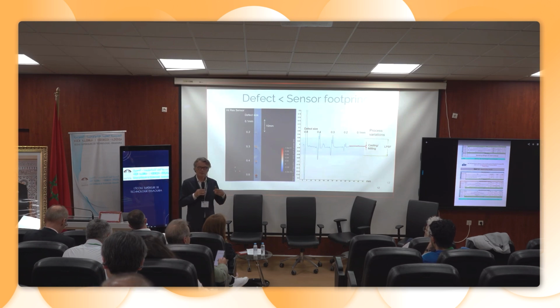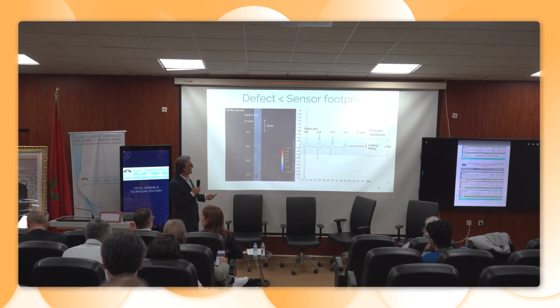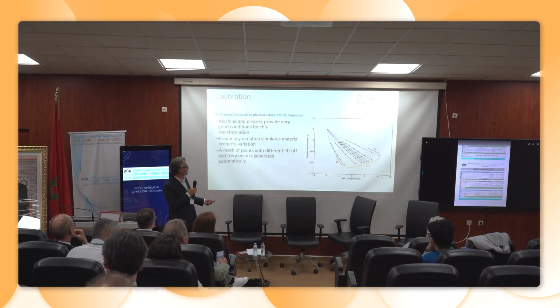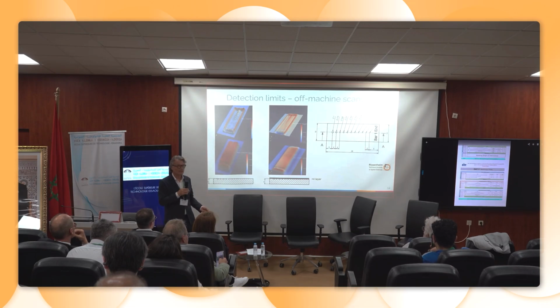Now, I will show what we can detect. So we are in a system where you deposit a new layer of material in order to detect defects on the surface. So I will show you here the ultimate detectability that we have with our technology. So this is for the RN6 project. This is a cast aluminum part. We have defects here from 0.8 to 0.1 millimeter, and we detect easily down to 0.1 millimeter surface breaking defects. Now, in the context of additive manufacturing, this is a bit more complicated because you have process variations, you have variation of the microstructure in your part, so it makes it a bit more difficult.